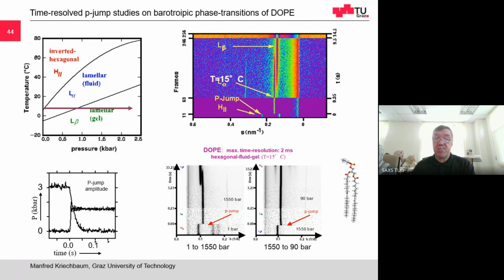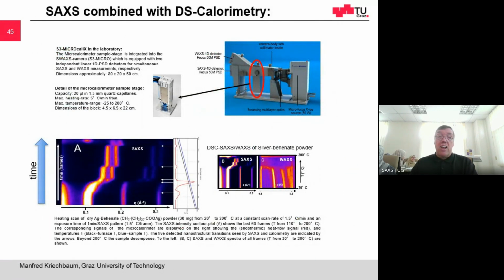So I will skip this. You can also combine small angle scattering with calorimetry when you make a heating scan. So we had a company build us a calorimeter, which we put into the SAXS camera. So here's a SAXS camera. We built in the calorimeter here. So we measure at the same time the heat signal and the change of the nanostructure.